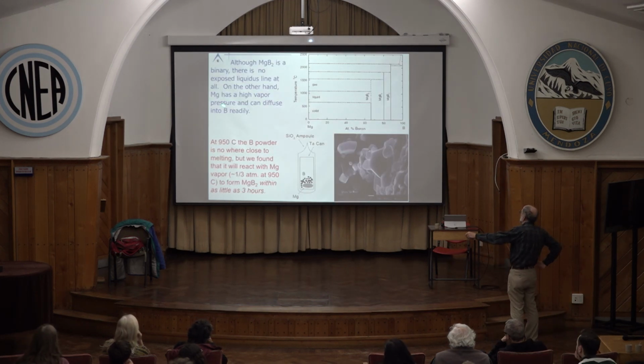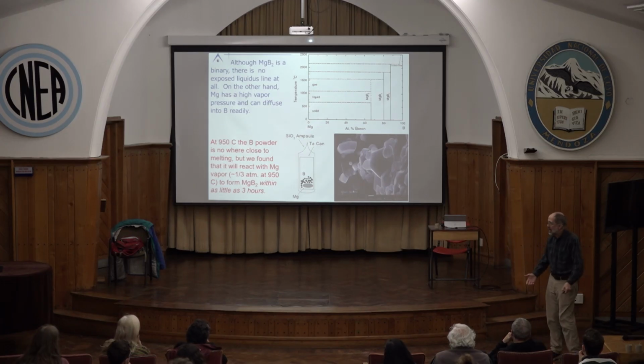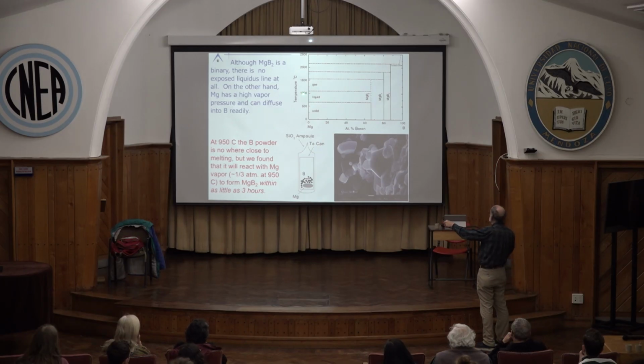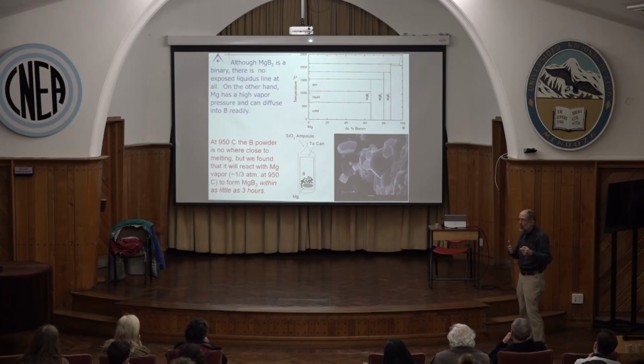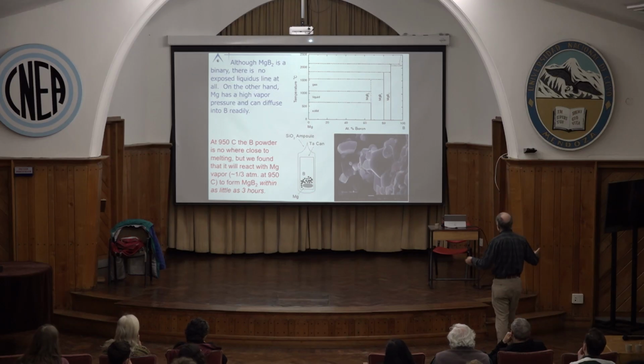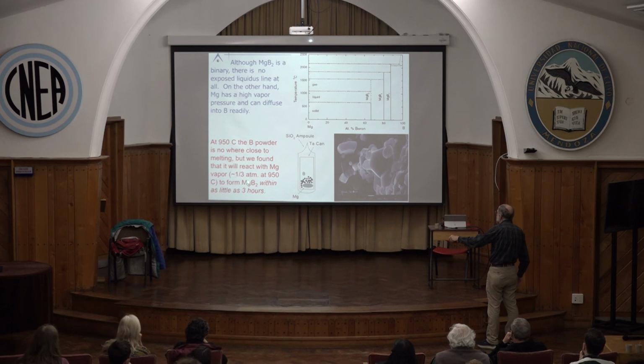Okay, now, having taught you how you grow things out of binaries, here's magnesium, here's boron, here's temperature. The problem is there is no liquidus line. The liquidus line is asymptotically plugged here, which means as soon as you get a little boron and magnesium, you immediately precipitate out MgB2. You can't grow nice large single crystals this way. And boy, we tried a lot. We tried tantalum tubes. But it doesn't matter. We figured out that you can get high purity MgB2 by reacting high purity boron with magnesium vapor.